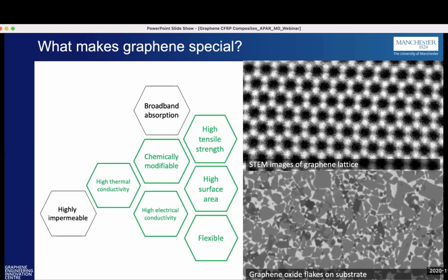Graphene is one millionth of the thickness of a human hair. But as a single layer, it is the highest thermally conductive material known to man, and the highest electroconductive material known. It's chemically modifiable, so we can adapt it to whatever we want it to fit, whether it's chemical resistance or putting it into carbon fiber prepreg, so it enhances the resin systems easily. You can add it to the resin systems a lot easier with functionalization than without.